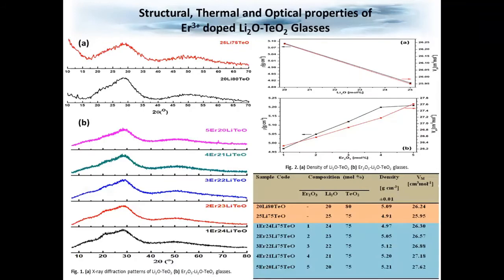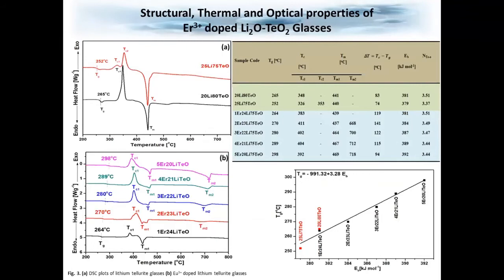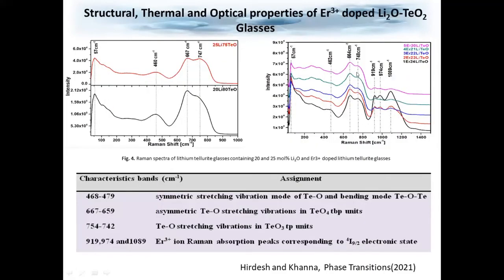Similarly, erbium doped lithium tellurite samples, we dope erbium oxide from 1, 2, 3, 4, and 5 mole%. The glass transition temperature increases with the increase in erbium oxide concentration. You can see the glass transition temperature increases from 264 to 298 on adding 5 mole% of erbium oxide. And you can see these Raman bands. There is not much significant change in the short range structure. And you see these bands in the higher Raman shift range. These are not Raman bands, but these are photoluminescence peaks.